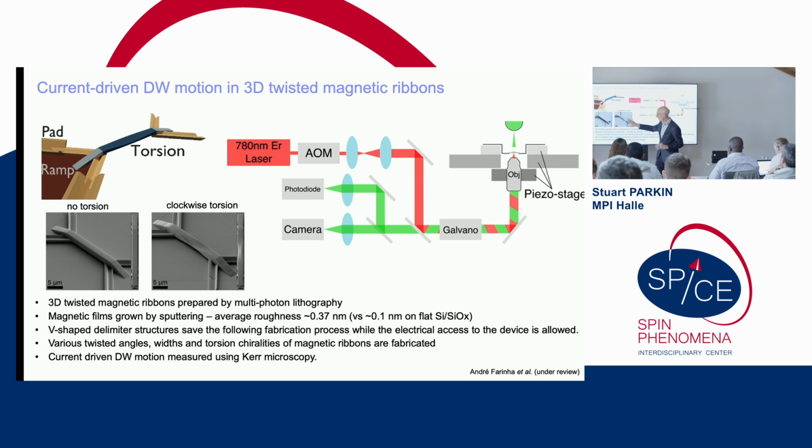And so in this way, and at the same time, what we're interested in then, as we heard this morning in Dennis's talk, for example, is how we can generate curvature and use that to generate new forms of exchange, DMI exchange, that will interact with the DMI exchange within the platinum, cobalt, nickel, cobalt structures. And so here we've introduced, you can see a torsion. So the structure actually bends one way, bends back again. For technical reasons, we need the surface to be flat at both ends so we can easily electrically connect to it without any additional lithography. Nevertheless, it's unimportant. We have 2 regions. We can twist it one way or we can twist it the opposite way.